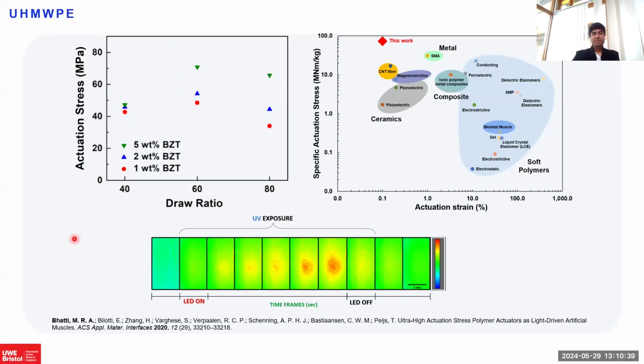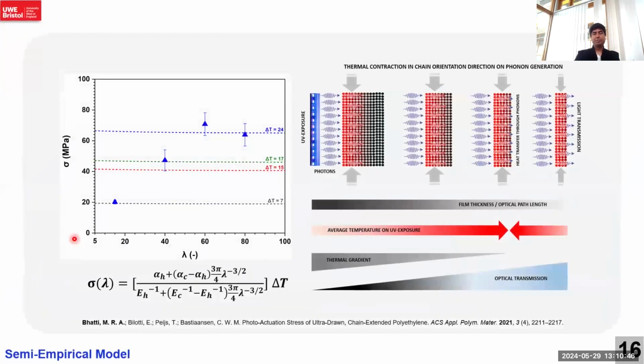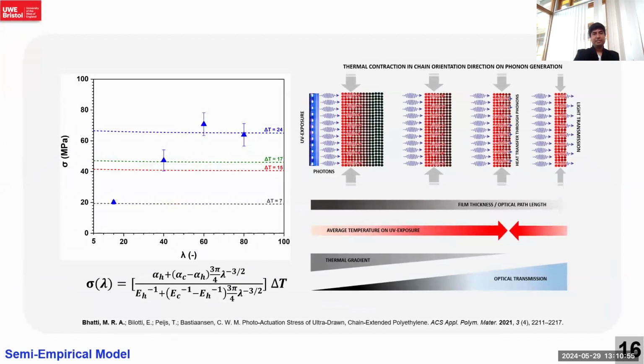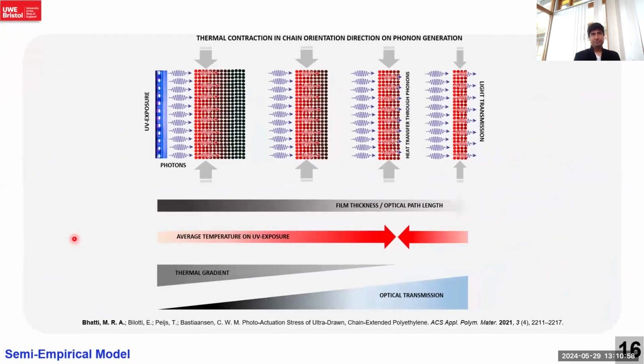But to analyze further what is the reason behind that, we devised a semi-empirical model. We theoretically analyze what is happening at a molecular scale, at a polymer level. So let's consider different types of films in terms of thickness and in terms of draw ratio. Let's say draw ratios of 20, 40, 60, and 80, or different film thicknesses like 30, 10, and maybe 8 or 5. These are the molecular arrays within the polymer, the polymeric chains, and we have BZT in there.